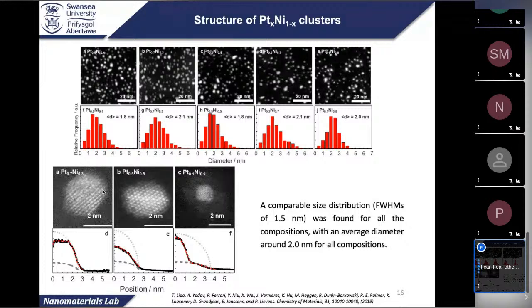The nickel-rich cluster, in figure C, you can see they formed a core-shell structure with a platinum-rich core and nickel in the shell, and the shell extends to a larger area because of the oxidation. So you basically get a nickel oxide shell, and the shell becomes larger and larger if you put it in the air for a longer time. But for all those 5 compositions, we got an average diameter around 2 nanometers.